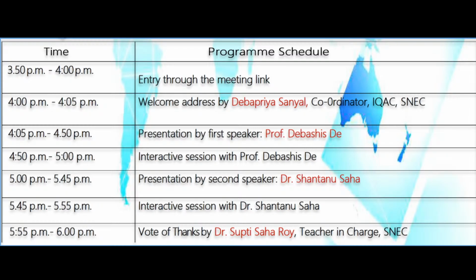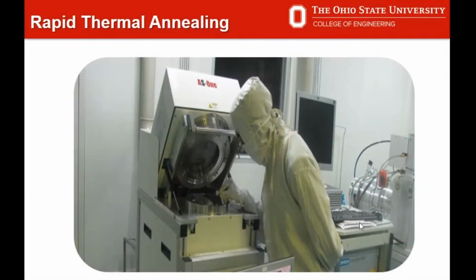So for rapid thermal annealing, the maximum temperature which is allowed in IIT Bombay is like 1100 degrees centigrade, and even in OSU they are not allowing us to go beyond 1200 degrees centigrade. So that is some kind of disadvantage if you use rapid thermal annealing. So the temperature is a big constraint here. And why is it called rapid? Because the temperature goes up very fast. So that's also a big advantage. So temperature is a constraint for rapid thermal annealing, while you could get it very fast. That is a big advantage.